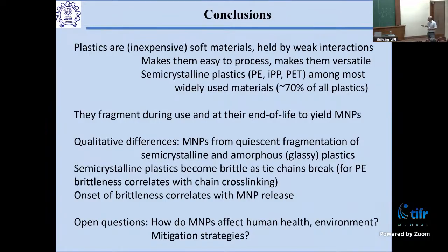But because they're soft materials, they're easy to process, they have really attractive mechanical properties, that makes them extremely versatile. And that's the reason we use a large part of this. Now, a large part of the plastics that we use, 70+%, are semicrystalline, and 40 to 50% is just polyethylene and polypropylene. Now, the part I didn't tell you about is it seems like polyethylene is much better than polypropylene for reasons that we are just starting to understand. I didn't have time to cover that.